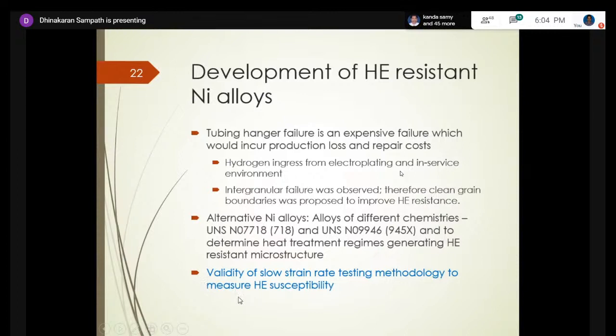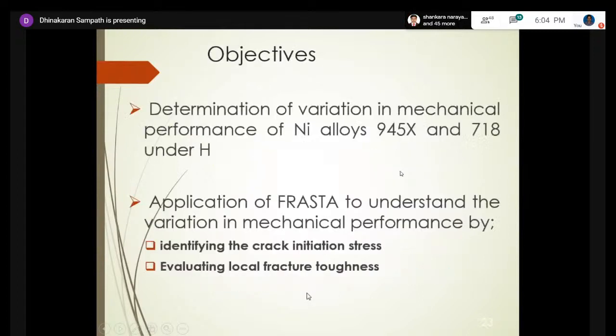In this segment, I'm going to evaluate the validity of the slow strain rate test methodology to measure hydrogen embrittlement susceptibility, because cracking is the main important thing. So we need to use fracture mechanics specimens, but the industries use slow strain rate tests. We are going to show why we should move to fracture mechanics specimens. First, we did a couple of slow strain rate tests. That's basically a simple tensile test, but at a very low strain rate, like 10⁻⁶ per second.